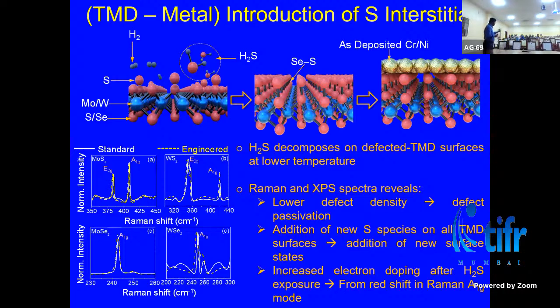So I'll pause here. Now we know how to create these defect sites, right? In case of graphene. Now we have to bring in these interstitials in TMDs, right, for our contact to work. So how did we do that? We figured out that the H2S actually decomposes at low temperature on top of these TMD surfaces. Now this is very interesting because H2S is the same source that we use for growing these TMDs.